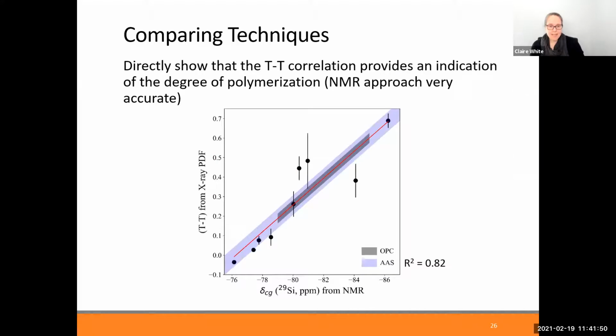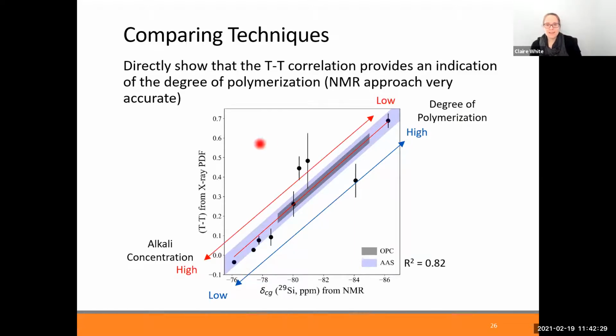And if we plot the (T-T) from X-ray PDF data against the center of gravity from NMR, there is some kind of correlation between the NMR and the PDF techniques. This is more just a curiosity kind of result that we found, but we thought it was interesting that even with PDF analysis, we can get a sense of relative differences in degree of polymerization. What you see here is towards the right, a high degree of polymerization on this plot, and towards the left, a low degree. And if we look at the amount of alkali the gels were synthesized under, there's a low amount in the upper right and a high amount in the bottom left.